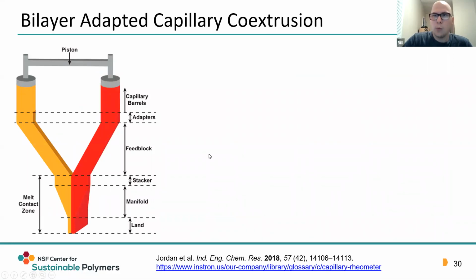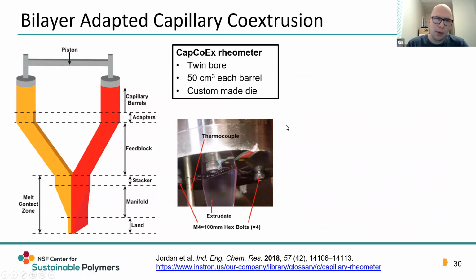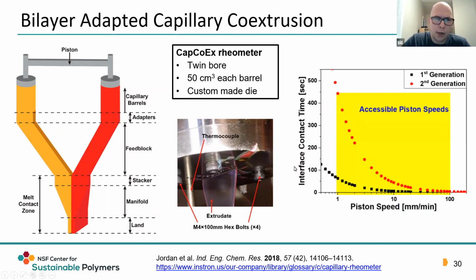Another way to make thin films, specifically a bilayer system, is the use of our capillary rheometer with two barrels that allows you to co-extrude two polymer melts together, where the limitation here is that each bore must be at the same temperature and piston speed. So you do have some limitations there that will alter your melt contact time a little bit. We're able to access a fairly wide range of interface contact times to examine in situ reactions, or if you're interested in localization at the interface, this might be a good small scale method for you as well.